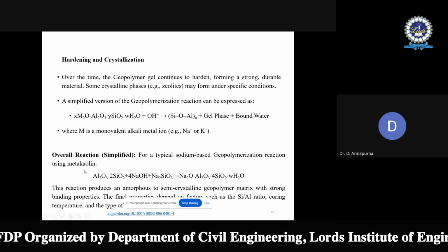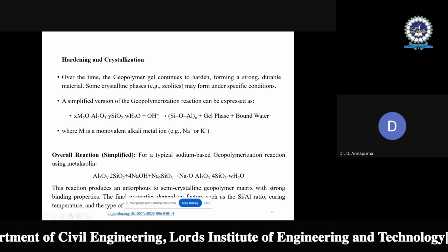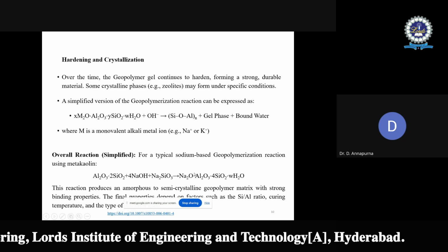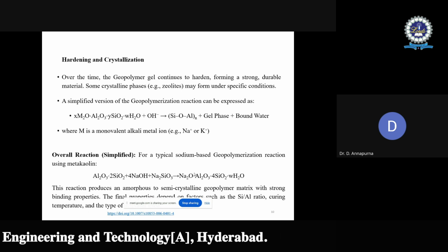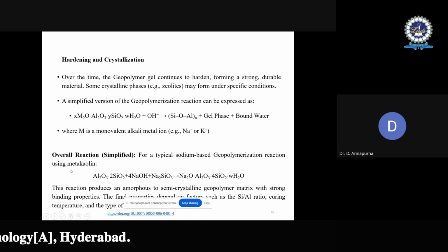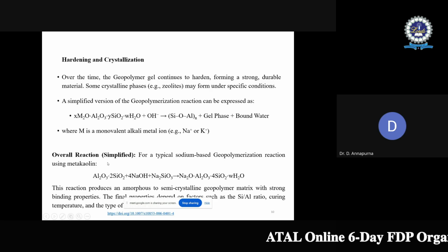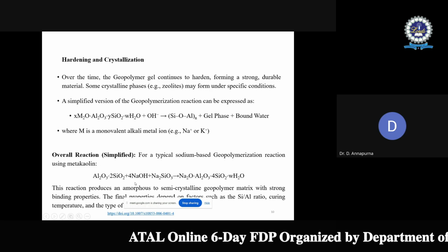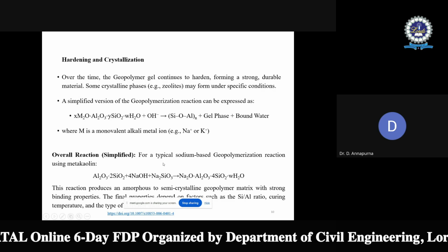So here the overall reaction, if we just take a typical sodium-based geopolymer reaction, which is specified by the earlier literature, is using the source material as metakaolin. Metakaolin, that is alumina and silicate, when it is reacting with sodium hydroxide and sodium silicate.